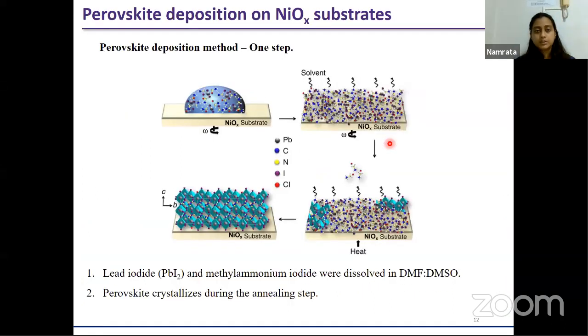The next step was to deposit the perovskite film, and for that we adopted the one-step deposition method. In this method, the perovskite solution is dropped on the nickel oxide substrate, spin coated, and annealed on a hot plate at a temperature below 100 degrees centigrade. During the annealing step, the excess solvent evaporates, and the crystallization of perovskite begins on top of the nickel oxide surface.